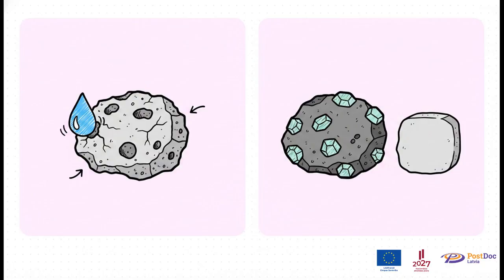But after the CO2 treatment, these materials are transformed. The carbonation products increase the solid volume, making the material dense, dropping the porosity, and locking away the CO2. It allows these waste materials to perform almost exactly like brand new, freshly mined aggregates. It's a real game changer.